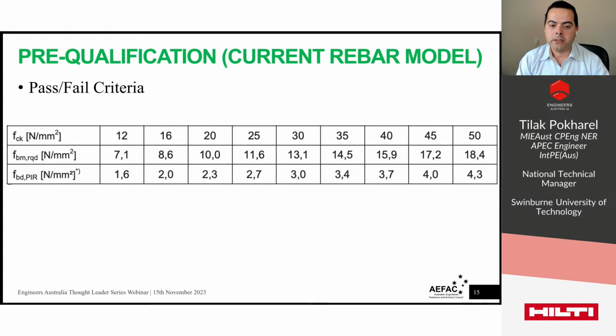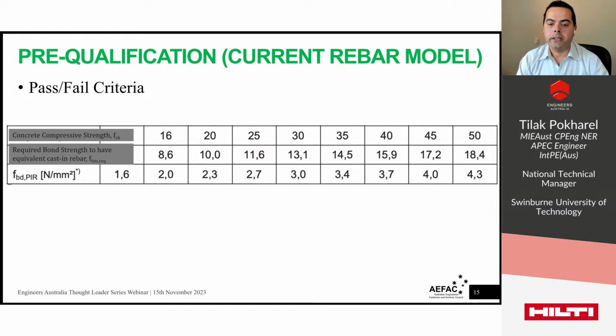Okay, there are three parameters in this table. The first one is the nominal compressive strength of the concrete. And the second parameter is the required mean bond resistance for the post-install reinforcing bar in assessment, equivalent to cast-in rebar. That means if the bond strength is equal to that value, then we can utilize the fbd PIR value, which is the third parameter. The design value of bond strength of PIR is used in design. Okay, it has different numbers there.